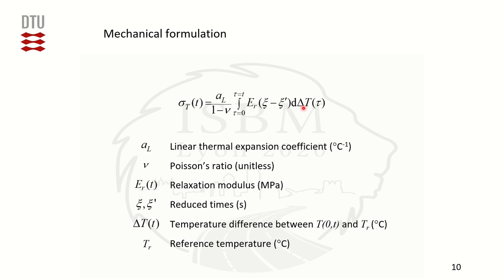Under a change of temperature delta T, this means that the half space does experience zero stress in the z direction and non-zero stresses of equal magnitude along any direction within planes perpendicular to the z-axis. The mechanical formulation aims at quantifying the thermal stress history specifically in the xy plane, where the low temperature cracking typically occurs. For this, a linear viscoelastic solid constitutive relation is selected, governed by one-dimensional relaxation modulus and a Poisson's ratio.